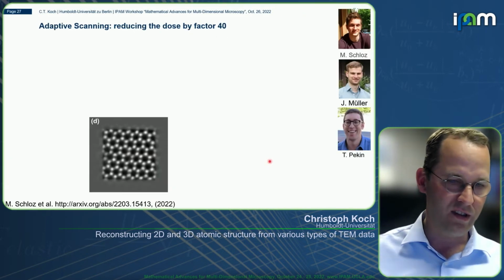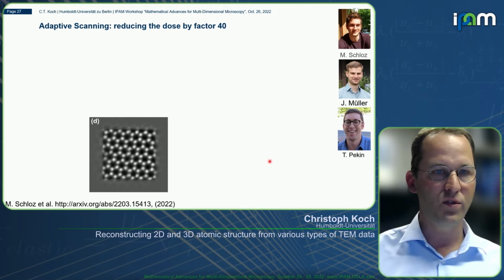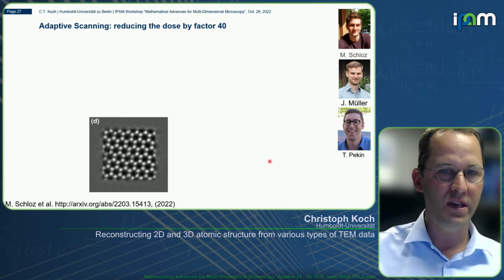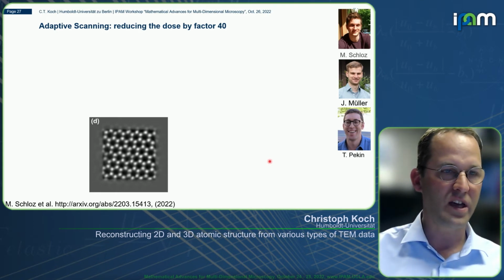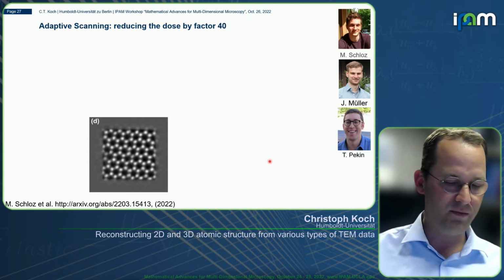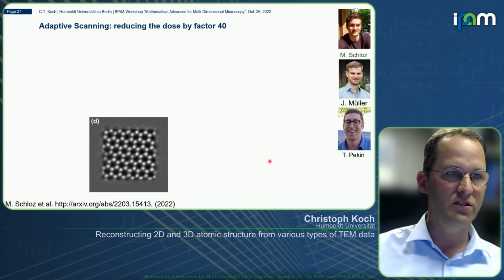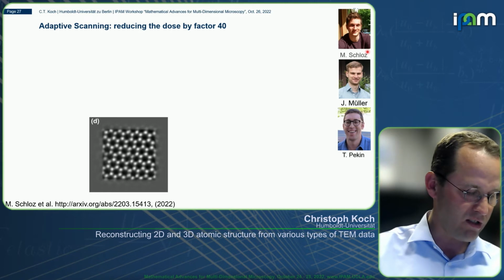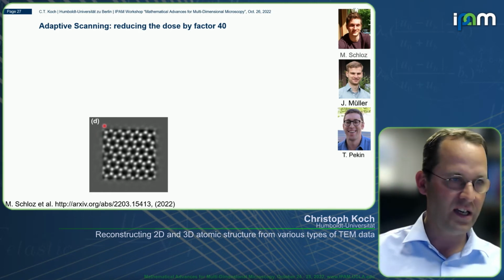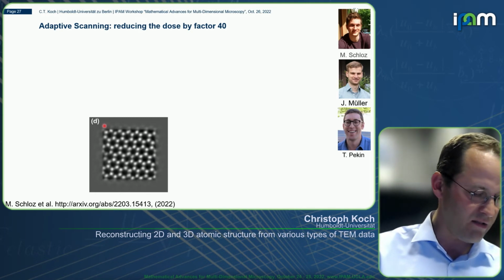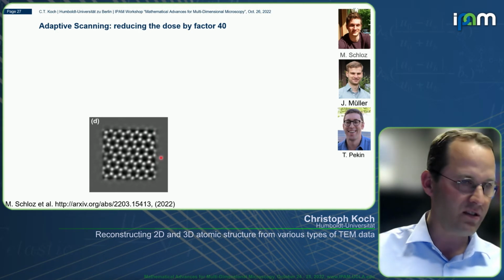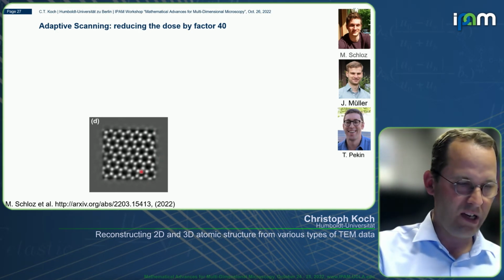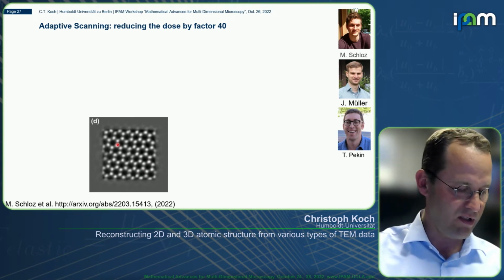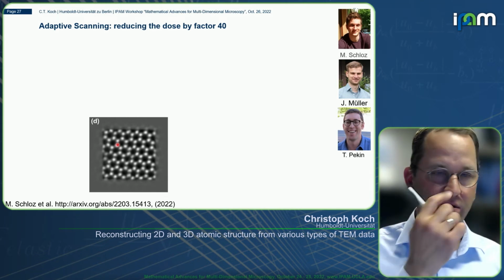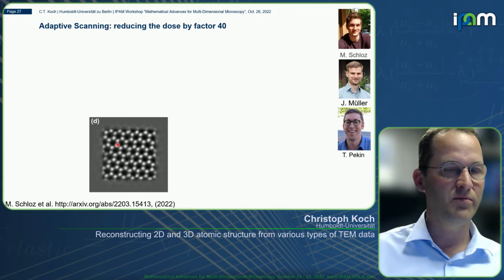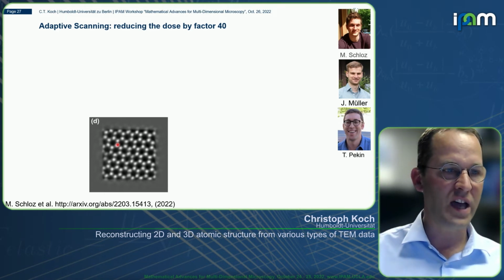So reducing the amount of data, but also the dose on the sample a lot, would mean that you want to position your beam over larger areas without sampling every probe position. That is what Marcel Schloz in my group has tried: reducing the number of probe positions. This is a full reconstruction of experimental data of molybdenum disulfide. It's not iterated very long, so the atoms are not very point-like yet, but I think for demonstration purposes this is sufficient. The question is: is it possible to reduce the number of probe positions by a factor of 40 and still get a faithful reconstruction of all the atom positions?